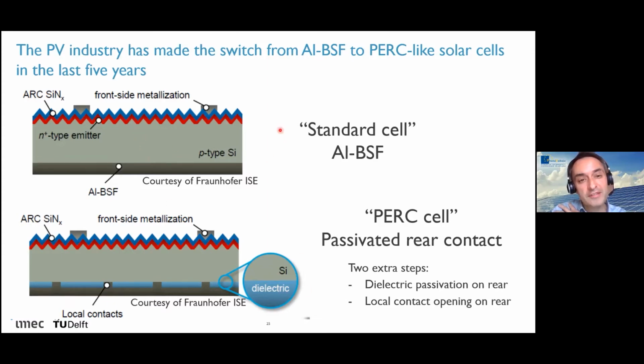So in this device structure, you have 100% of the rear surface in direct contact with aluminium. In this cell structure, it's only a few percent of the rear silicon that is in direct contact with aluminium. The rest is really passivated with this dielectric layer that is in between the silicon and the aluminium.